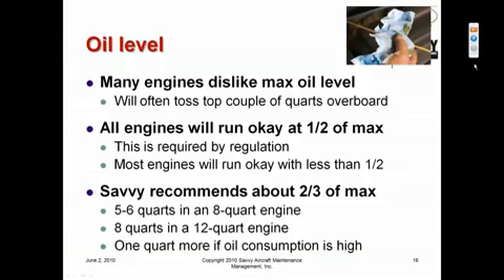We manage about 7% of the Cirrus fleet, and those have 8-quart sump capacities, and we typically run them between 5 and 6 quarts, and add a quart when it gets down into the 4s. If you have 12 quart capacity, like in the engines on my 310, 8 quarts is about right, and that's typically where I run my engines, and I typically will add a quart of oil when it gets down to 7.